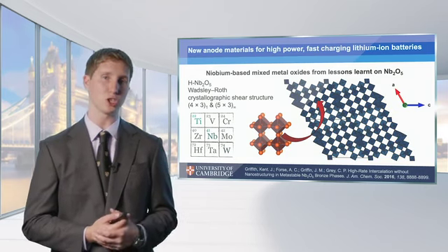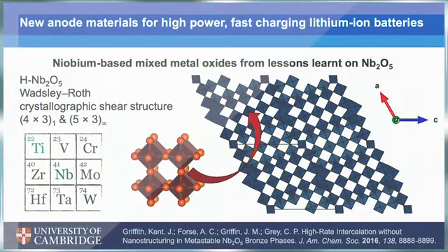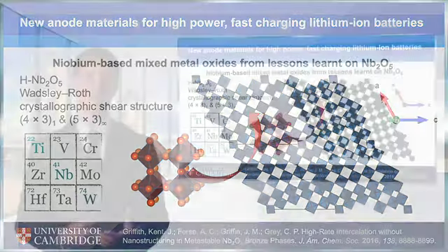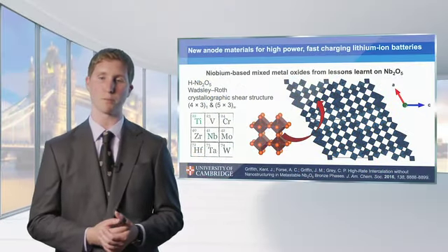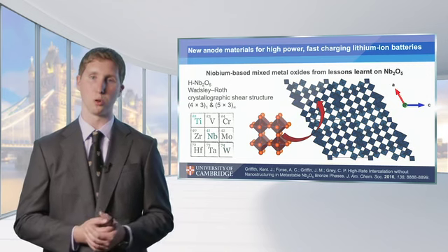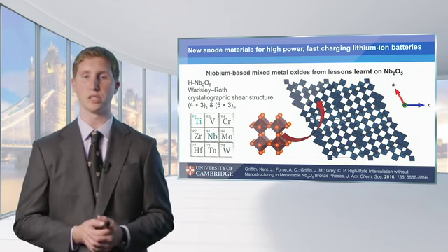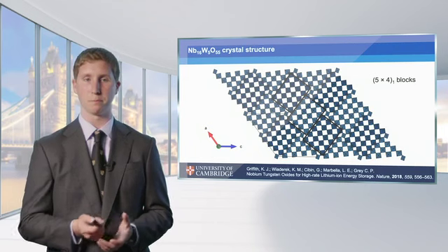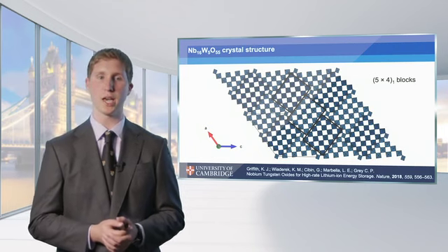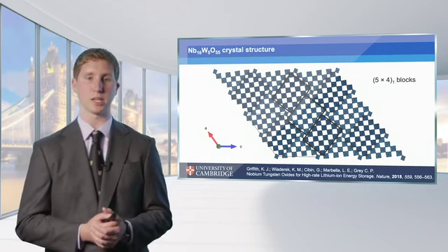This structure type doesn't just occur, though, in pure niobium oxides. So like in the titanium niobium oxide that Toshiba's working on, most of the early transition metals and some things further afield in the periodic table can actually be incorporated. You can change that metal-oxygen ratio, and you can get different block sizes, different arrangements, and different structures based on this crystallographic shear motif. And so in our case, we took what we learned about this to explore a whole series of these compounds. And the one that I'll be focusing on today as the most promising from our studies